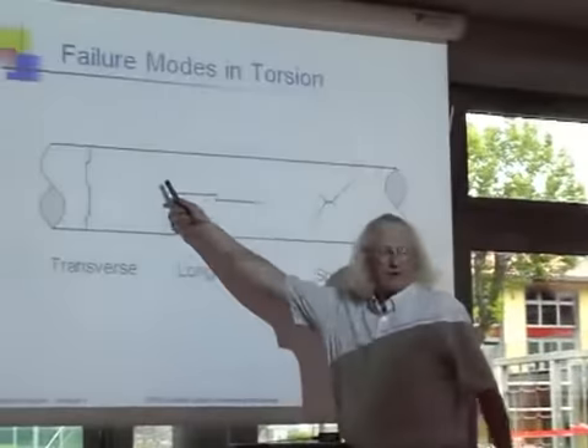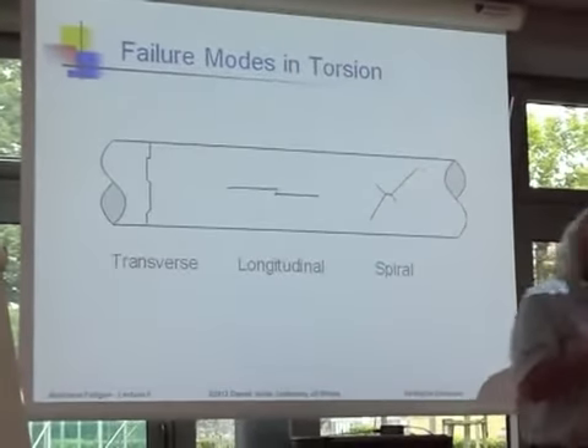And if I decrease the stress level some, and again do the same torsion test, now the failures all run along the length of the bar. And then finally they grow into the depth. And this is the intermediate regime. And so I call this the longitudinal fractures.